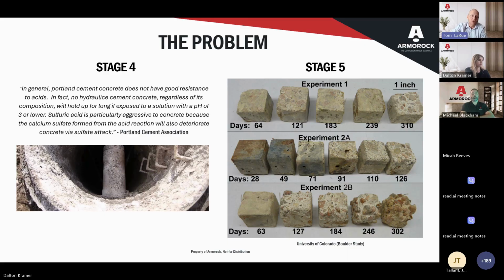not what we see throughout the country. We'll regularly encounter highly corrosive structures with ppm in the thousands. So 150 is fairly typical of a structure across the country. You can see in less than 1 year, the amount of deterioration of that Portland cement, leaving just some large aggregate. That is extreme structural deterioration, becomes a danger to carrying traffic loads, and increases I&I. And as we've talked about, the rate of corrosion is going to increase. So that's the corrosion cycle.